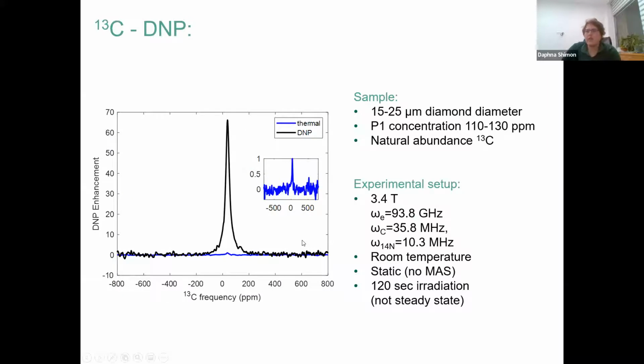And here you can see DNP enhancement of carbon in a diamond powder. The powder is 15 to 25 micrometer in diameter, and the concentration of the P1 center is about 120 ppm. Everything is natural abundance, and we're working at 3.4 Tesla, which is about 94 gigahertz for the electron and about 36 megahertz for the carbon. So all these experiments that I'll show you are room temperature without magic angle spinning.